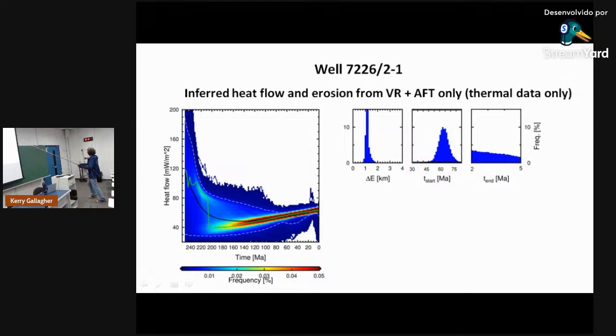And so for the heat flow, for this well, we get something that looks like this, based just on vitrinite reflectance and also some fission track data. I can't remember exactly what we had as data, but just these data that are sensitive to temperature. And we saw already there was that little trade-off between erosion and heat flow or temperature. So in this case, we have to try and estimate heat flow and the amount of erosion. Okay, so this is our estimate of erosion. We also have an estimate of the start and end of the erosion event. So we don't know that very well.